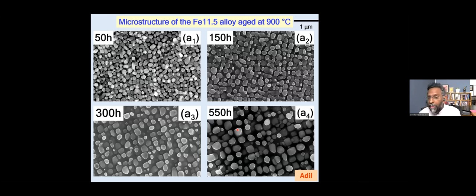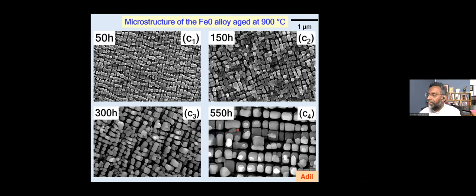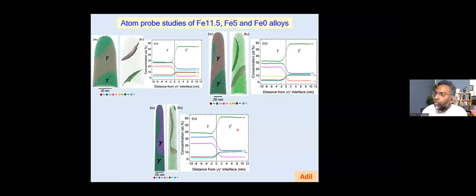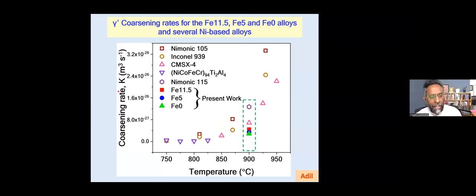Okay, and when we look at these growth kinetics of these materials, we also try to see whether these growth kinetics can be associated with interfacial energies between the gamma prime and gamma. To know the interfacial energies, you need to know the interfacial composition. Again, we went to atom probe and tried to find out the composition of gamma and gamma prime, and from that get an idea of the interfacial energies. And from that interfacial energy, we try to calculate the coarsening rate. How do they coarsen? That means how do these particles become bigger? What is the rate at which the particle size grows?